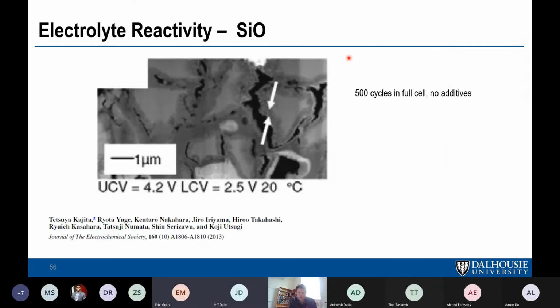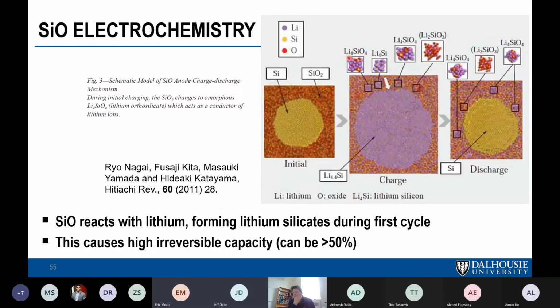So Mark, the first time you cycle, you lithiate this composite, you get what sort of volume expansion? It depends which voltage you go to, but typically, well, like I said, it will expand exactly the same as pure silicon. Versus silicon, yeah. So that was 280%. So this will be about the same, irrespective of oxygen content. Got it.